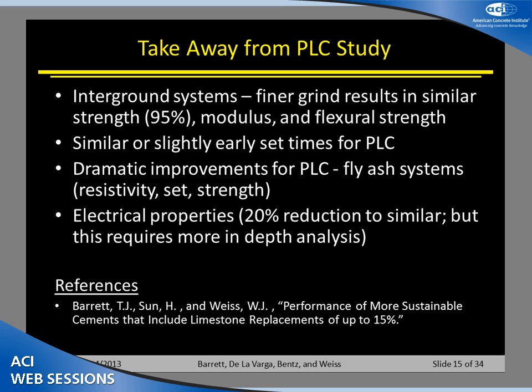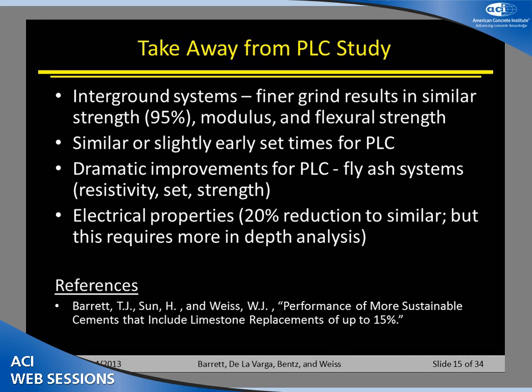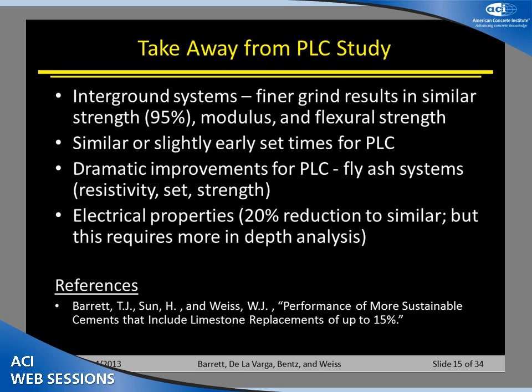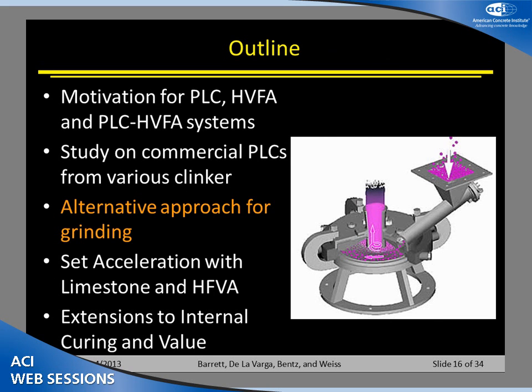So really the takeaway from the PLC systems, the intergrind systems, is that a finer grind results in similar strength. They're always within 95% of the parent material. Very similar modulus, very similar flexural strength. We see similar or slightly earlier set times as compared to the OPC when we're looking at the PLC systems. And then for the electrical properties, as I mentioned, on some systems, depending upon the chemistry, we can see a slight decrease, but we see very similar chloride ingress in those particular materials.